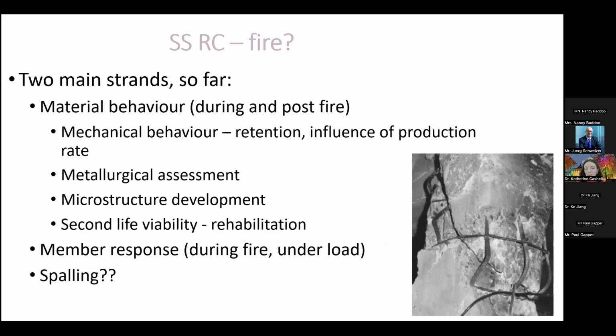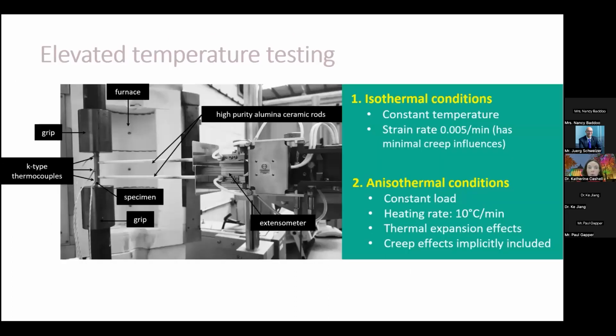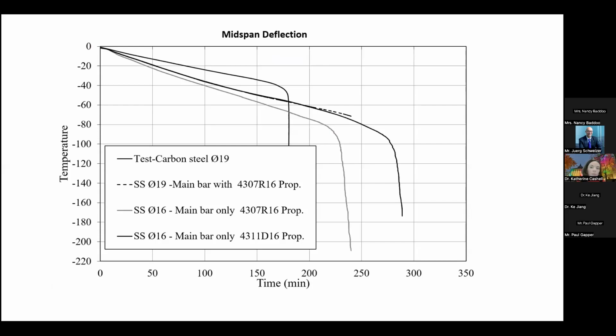Again, we've looked a little bit as well at fire, so trying to understand the mechanical behavior, the retention of strength and stiffness when a concrete structure might experience a fire scenario, and a little bit on spalling, which I'll come to in a minute. This is just an image from some elevated temperature tests that we've done to try to understand the material properties. And here we can see some reinforced concrete members with carbon steel reinforcement and stainless steel reinforcement in fire. And you can see, hopefully from this, that the member with stainless steel reinforcement outlasted and performed much better than the carbon steel reinforced concrete member in that fire scenario.